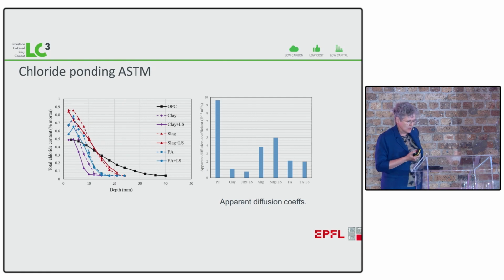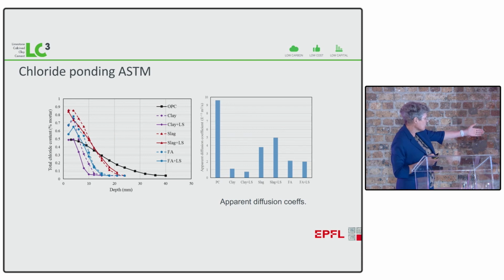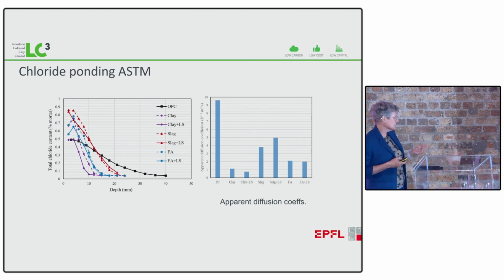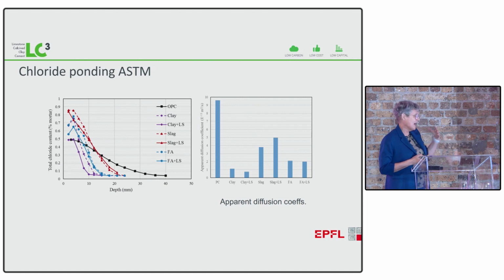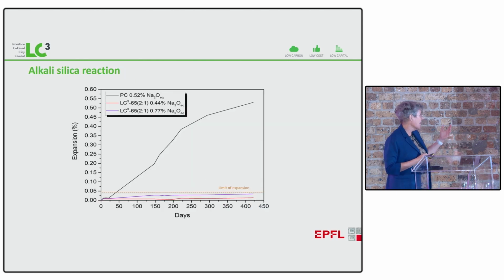This table here shows the chloride resistance, where we simply put the cube in a solution of chloride. The black curve is the reference Portland cement. The red ones are the blends with slag, which you see improve the situation. The blue ones are the blends with fly ash, which improve it again, but the best of all are the purple ones, which contain this blend of calcined clay and limestone. So you get better resistance to chloride penetration than you do with fly ash, and better early strength, and very good resistance to alkali silica reaction.